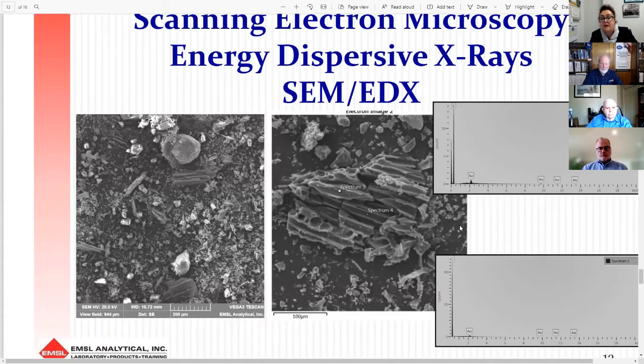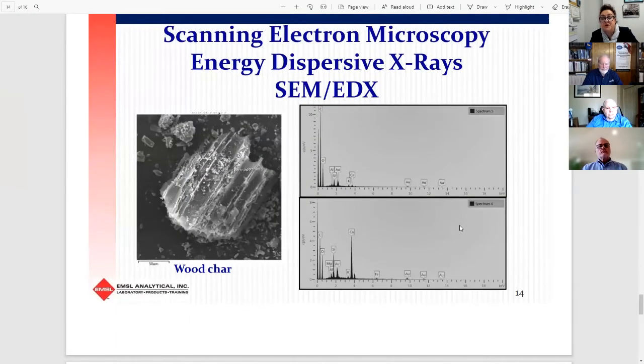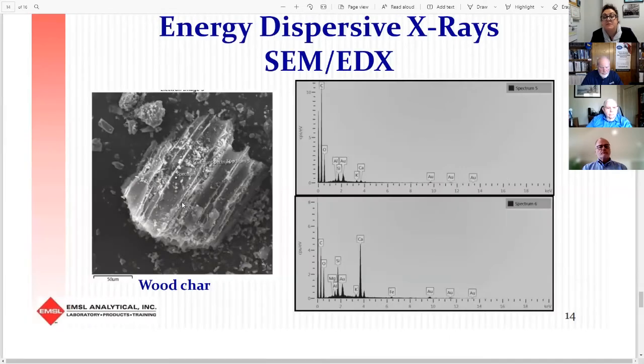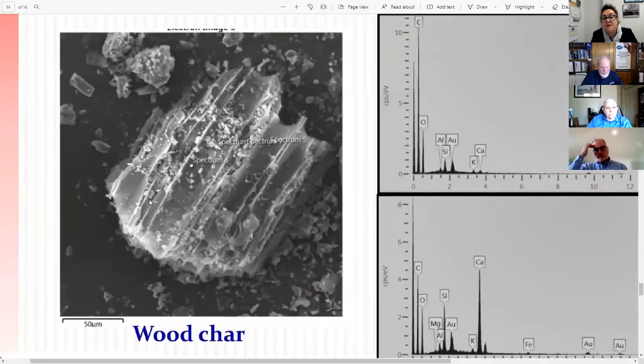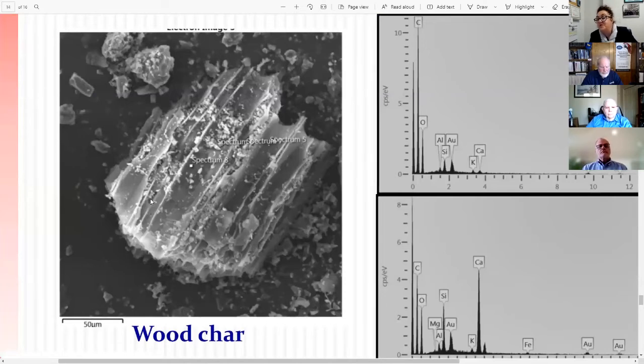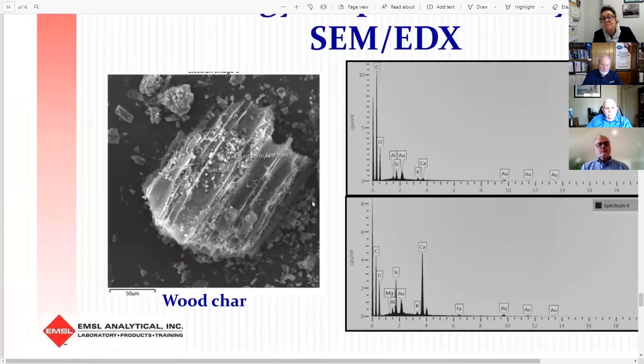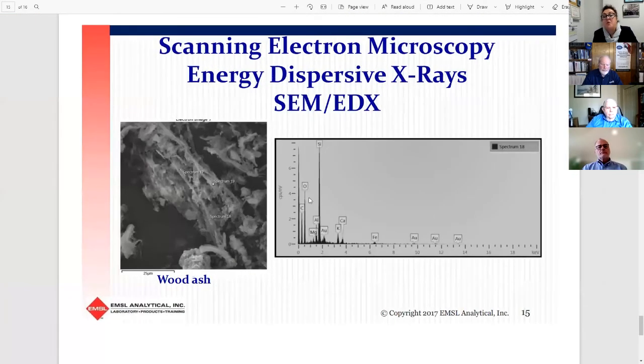On the next slide, there is another picture of wood char. But in this situation, the pyrolysis, the burning, is more advanced. The structure is a little more brittle, it's more degraded. And if you look at the elemental composition on the right, it's not only carbon. So it started to ash already. It has some silicon, it has potassium, aluminum, calcium. So it starts to degrade more, and that's how we end up with ash, because we were talking about the difference between wood, char, and ash. It is the degree of pyrolysis. More carbon in char, and then it starts to go away by burning, and you end up with ash, which is mostly mineral.